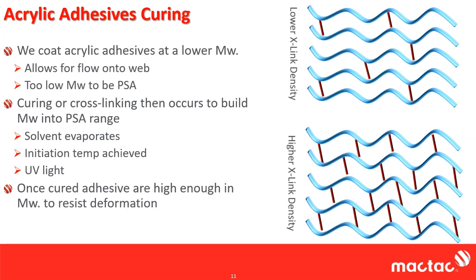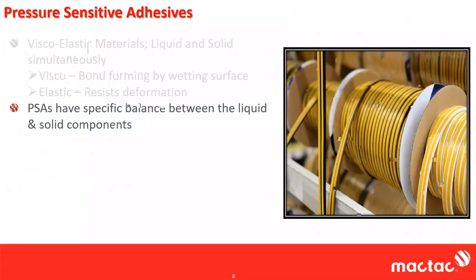And on the right hand side, I just have 2 examples here. I have something of a lower cross-link density. Each one of those is a rough exaggeration of what it looks like, the blue being the polymer backbone of the acrylic, and the red just being the cross-links. You can have low cross-link densities. You can have high cross-link densities. With solvent-based adhesives, you can even throw in an extra cross-linker and firm it up. There's no set cross-link density per se. This is one of the ways with acrylics you can tune the properties, is how much cross-linking you have in there.